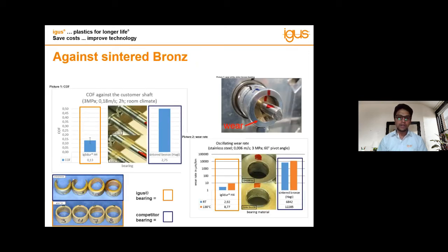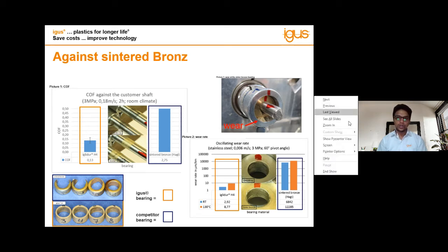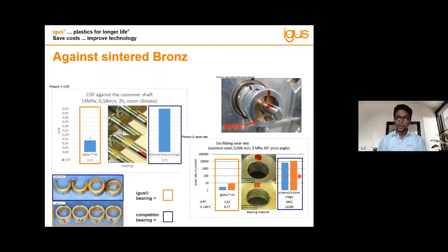The third case study we have done is with sintered bronze, that is powder metallurgy. Most of our customers know that these kinds of sintered parts are more used in high RPM applications. But when these parts are used in oscillation applications, you can see a test performed at 3 MPa, which is a very low load, 0.3 kg per mm square, at 0.18 meter per second at room temperature. You can see the complete disintegration of the part from the first figure to the last, so there is no material left here.